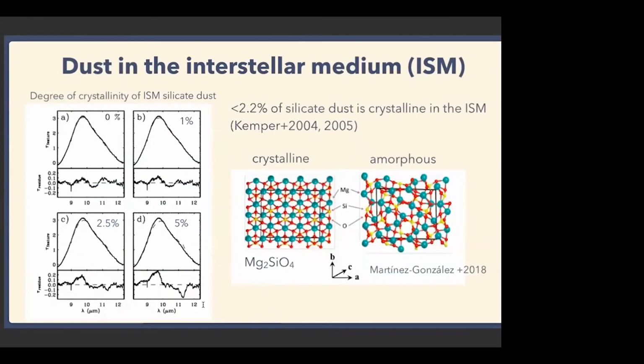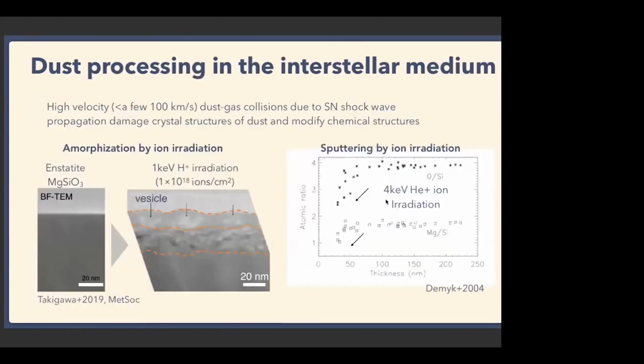There are basically two types of destruction processes of dust in the interstellar medium. One is dust-gas collisions. Dust-gas collisions are the main cause of the amorphization of dust. This is an observational study to estimate the degree of crystallinity of interstellar medium silicate dust. They showed that less than 2% of silicate dust is crystalline. Again, the difference between crystalline dust and amorphous dust is the degree of ordering of the atoms in the dust. This amorphization may occur through high velocity gas-dust collisions.